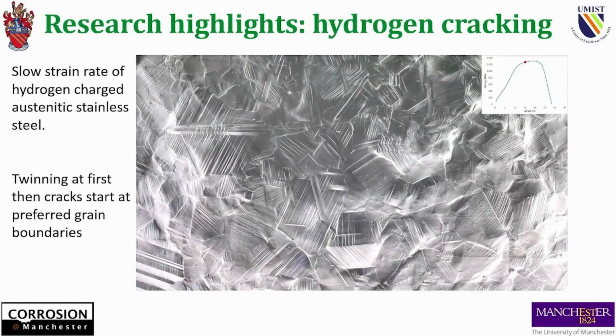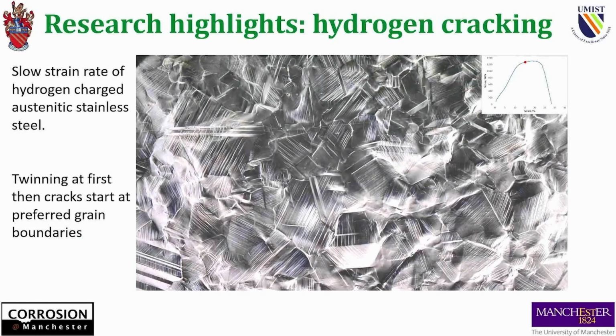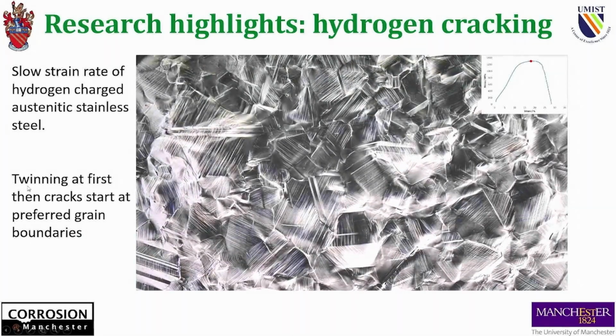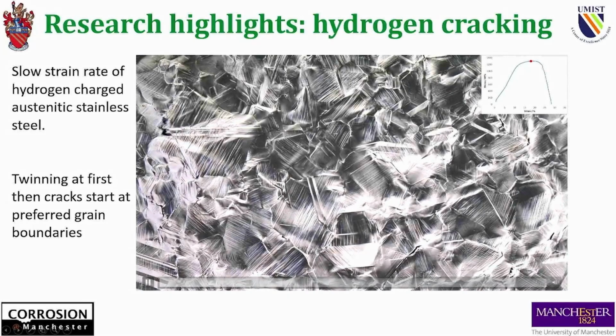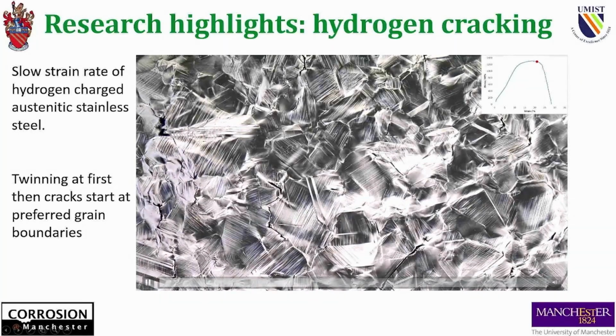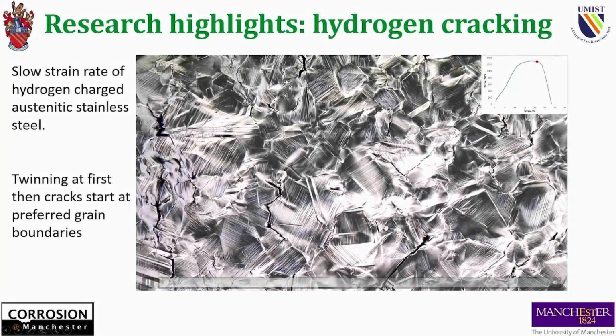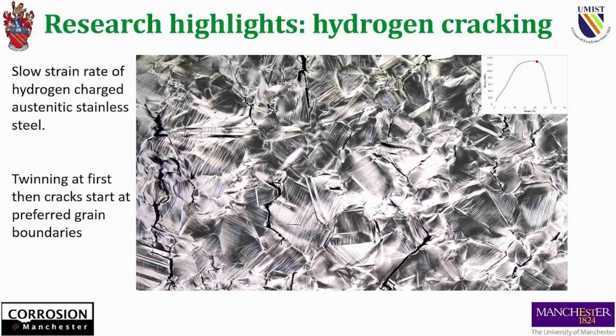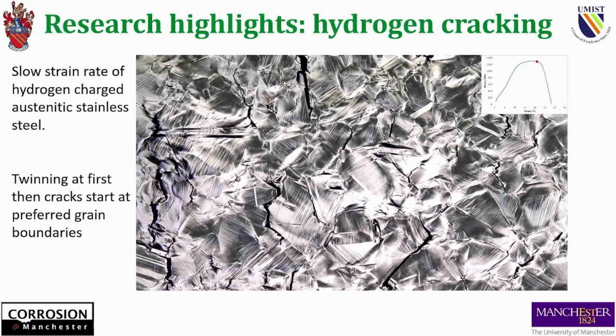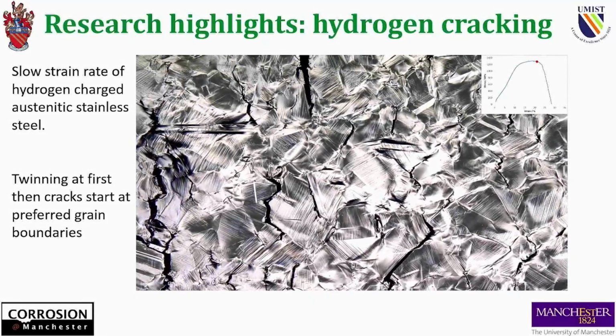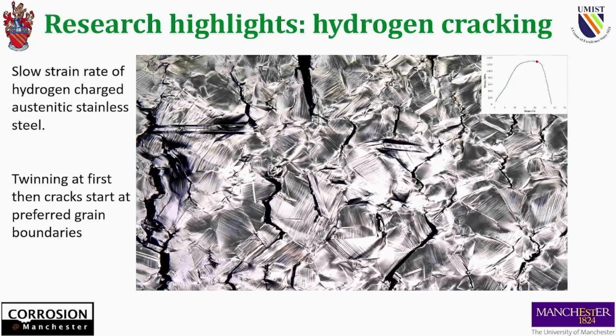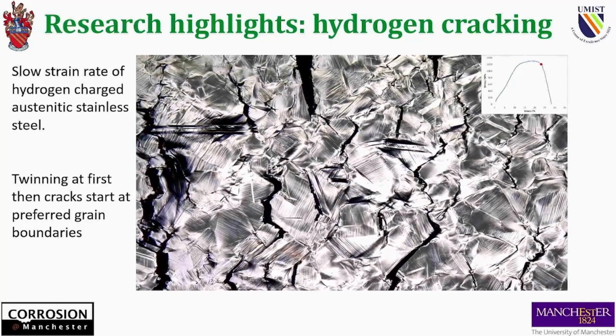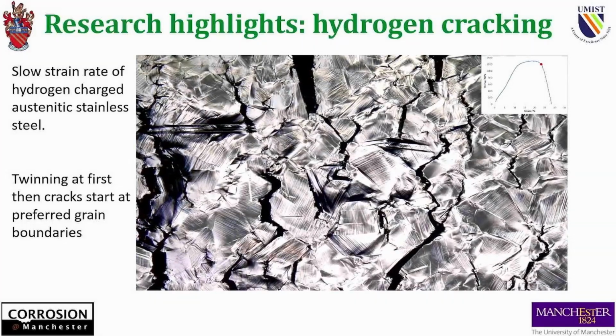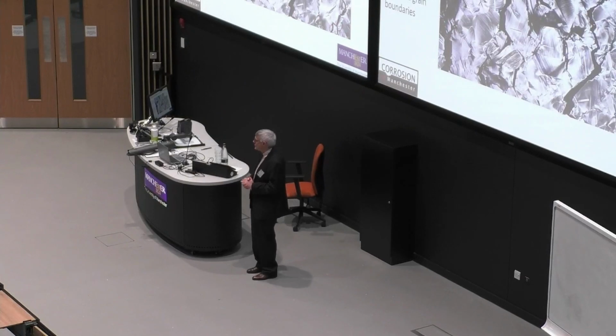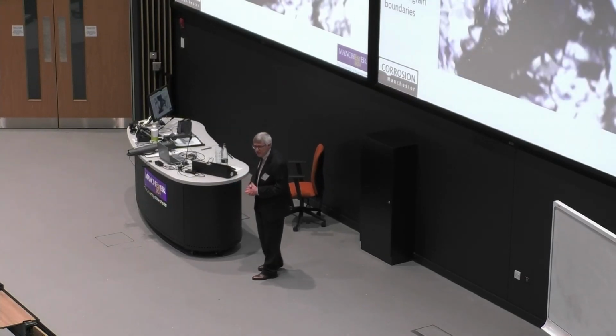You can see the twins beginning to develop in the grains, and you will eventually see cracking happening around about here. You can see cracks beginning to develop there and here at the grain boundaries. This is not a sensitized alloy, by the way. This is just where the triple points come and load up. Eventually it will break. If you want to ask about this, then Dirk knows all about it. But that's a time-lapse photograph using confocal optical microscopy on a cracking piece of austenitic stainless steel, which in a sense shouldn't really hydrogen crack in the first place, but it does. And finding out why it does is really important for many industries, including oil and gas and others.